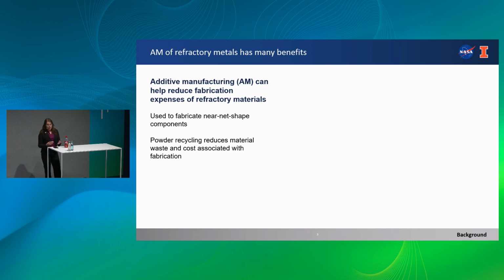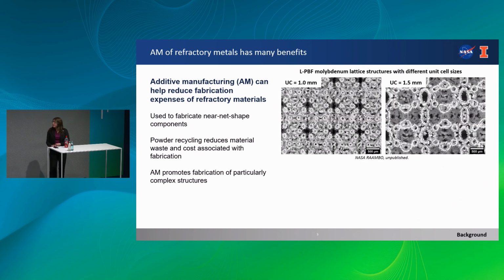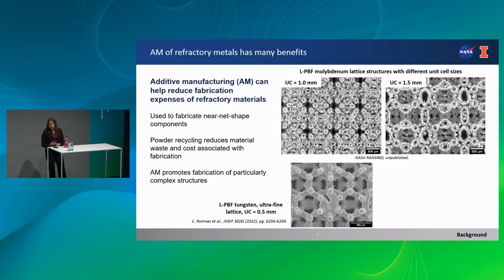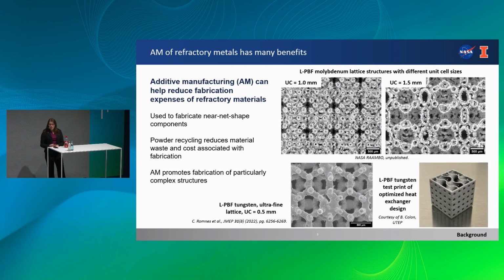We can obtain near net shape components, and powder recycling allows us to help reduce the excess material that's wasted. Additionally, one major benefit that is much greater than the traditional machining techniques is the fact that we can fabricate particularly complex structures. So as you can see here, in some of our previous work on ultrafine lattices, we can actually print these refractory metals into very complex structures and can actually adjust the design based on the application of interest. Additionally, you can print these types of materials in complex geometries for things such as heat sinks, etc.